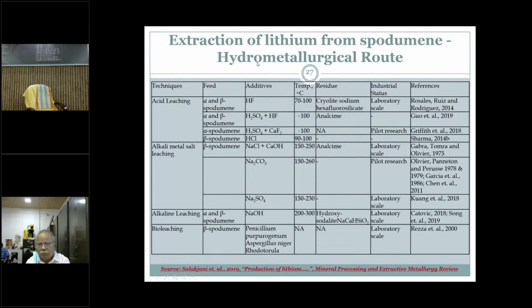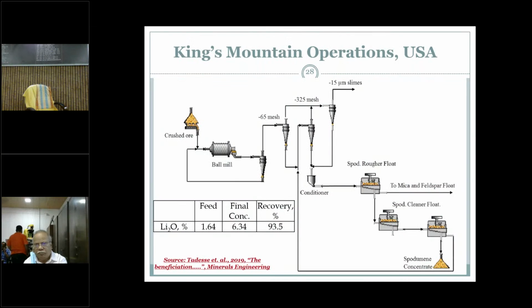And the hydrometallurgical route is mainly the conversion of alpha to beta spodumene followed by acid leaching. Before that, this conversion will be made with high temperature applications, and after conversion to beta spodumene, it will be subjected to different acids. Alkali leaching, etc., have also been tried by some researchers. And in our institute, Dr. Nilotpala Pradhan is trying a couple of bioleaching experiments to recover the lithium from spodumene concentrate. This is some general information available on the Kings Mountain operations, United States.